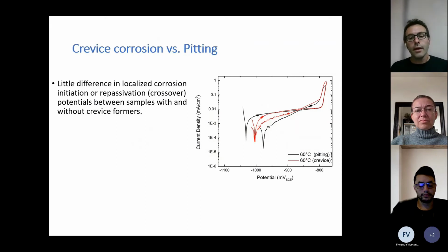So in those kinds of tests, we take the metal and we polarize it first in one direction, localized corrosion starts to occur here, and then we reverse the scan direction, and eventually it repassivates when it crosses the forward scan. And when it crosses the forward scan, here we can define the localized corrosion repassivation potential. And this would be the localized corrosion initiation potential, right?